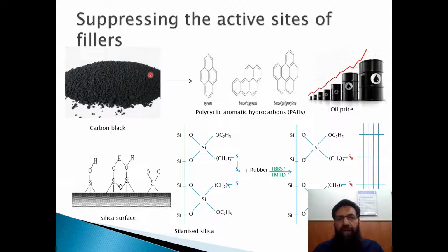That's why most people are now moving from carbon black to silica. Number one is the carcinogenic effect. Number two, the performance which we can get from the silica after treatment would be much more as compared to the performance that we get from the carbon black. And also nowadays, oil prices are hiking, and with the increase in the oil price, carbon black is also becoming a bit more expensive. So silica would be the better option as compared to the carbon black. We did use the different fillers in our.